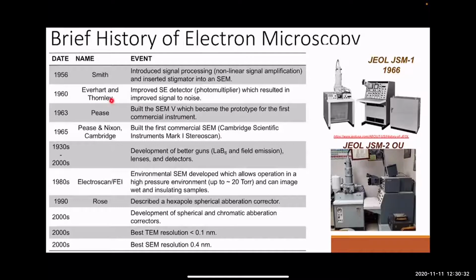And there's a very famous Everhart and Thornley SEM detector that's to this day on almost every SEM that circumvented that problem. And really, the Everhart-Thornley detector is fairly simple in and of itself, and the main part of it is just a photomultiplier tube. So anyway, taking us down to the 2000s, 20 years ago, you're now at a point where people are just improving lenses and sources, electron sources, everything about the systems. And we're getting down to, again, in some cases, atomic resolution on an SEM and subatomic resolution in the tens to hundreds of picometers on a TEM. So pretty incredible.